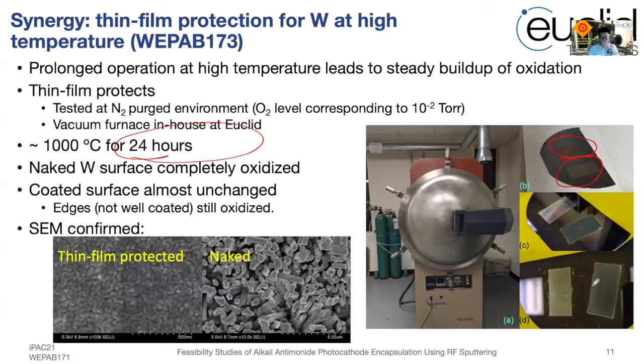We realized that the surface color has very significant difference between these two wafers. And you can see that for the naked tungsten, it has already completely oxidized, at least for the surface. However, from this photo, it is seen that the surface of the tungsten is still preserved and it has a metallic look. So whether it is really oxidized or not can be seen from the SEM inspections. So for the thin film protected, you can still see the thin film structure on the surface with the indication that there's somehow some oxidation, either at the very, very shallow surface of the tungsten underneath of the thin film. But we are confident that the SEM had registered the silicon dioxide thin film structure only. So this will be done in a more systematic way in our future studies.